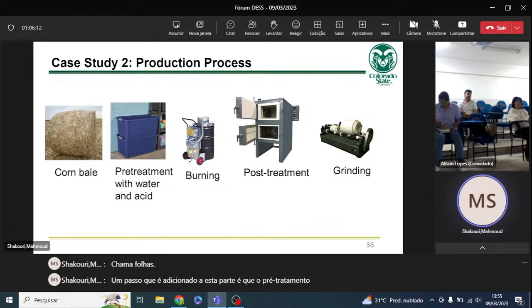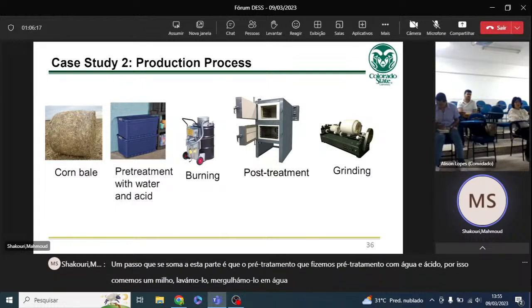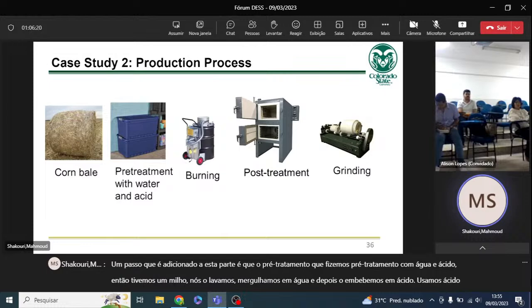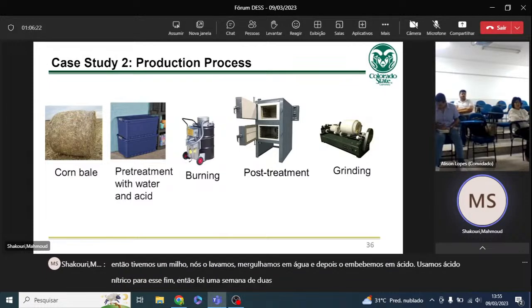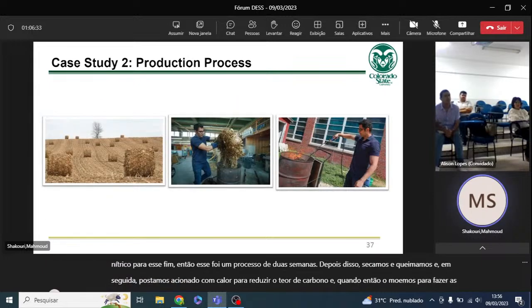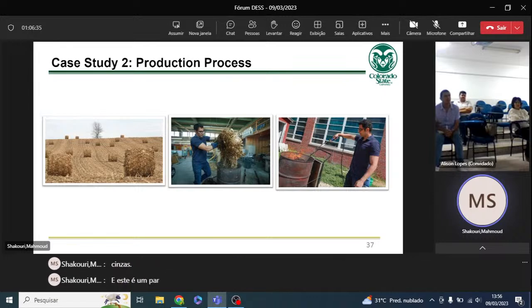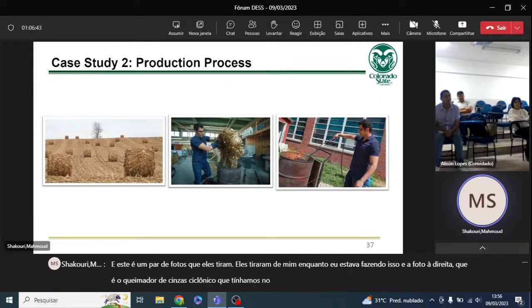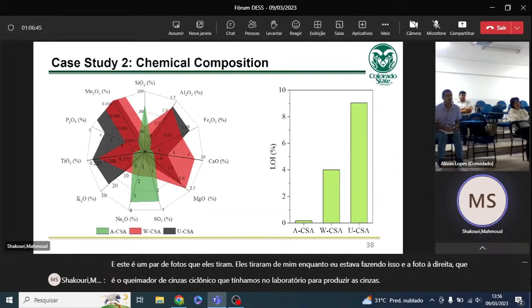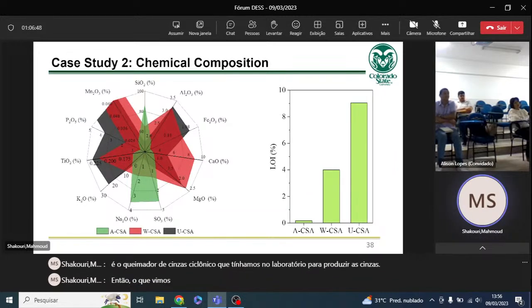We did pre-treatment with water and acid. So we had the corn, we washed it, we soaked it in water, and then we soaked it in acid. We used nitric acid for that purpose. So that was a 2-week process. After that, we dried it and we burned it, and then we post-treated with heat to reduce the carbon content, and then we ground it to make the ash. And this is a couple of pictures they took of me while I was doing it. And the picture on the right, that's the cyclonic ash burner that we had in the lab for producing the ash.